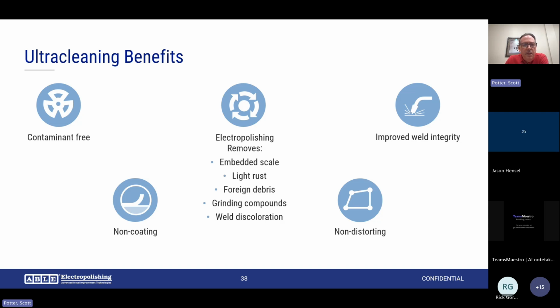And then as far as removing, it removes embedded scale, very light blush rust, foreign debris, grinding compounds. It removes weld discoloration as well. Also, a lot of people use it to improve their weld integrity. Want to make sure that they're welding onto a good clean surface so they get a stronger weld. And again, it's non-distorting. With the electropolishing, you don't have to worry about electropolishing parts that are thin or fragile. We can typically electropolish a part up to about 4 thousandths thick. It's about as low as we can go.